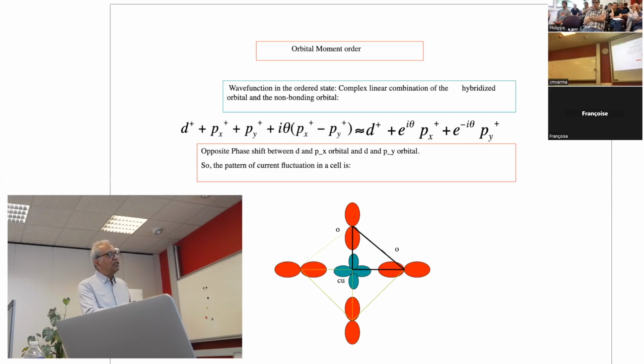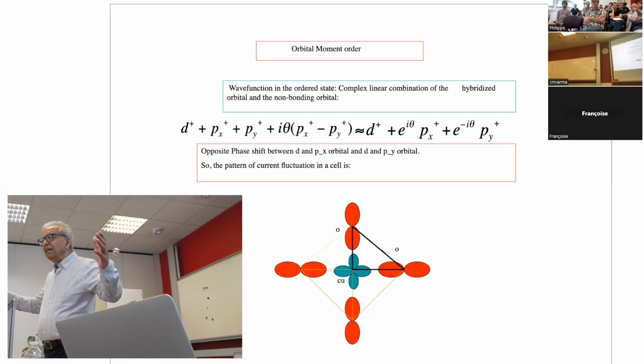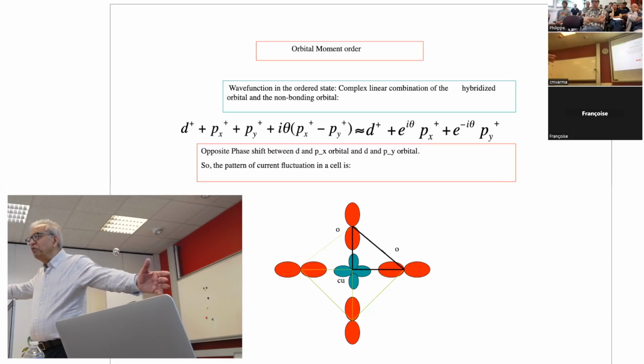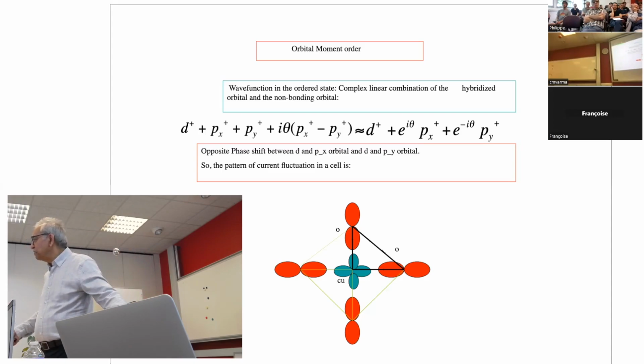That means that the new Wannier orbital is a complex orbital, d dagger plus e to the i theta px dagger, theta small, plus e to the minus i theta py dagger. And what that means is that going from copper to oxygen, you have a phase, which means that there's a current flowing. And if there's a current flowing in this triangle, rule of life, current loops cannot flow indefinitely. That's always an unstable state. And I don't want to change translational symmetry. It means I have to close the loops within the unit cell.